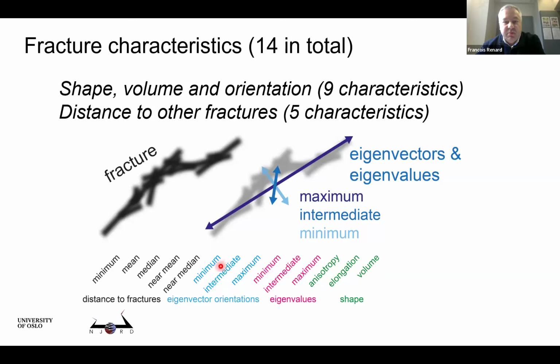There are 3 parameters that correspond to the length of the fracture. We fit each fracture with an ellipsoid, and we use the dimension in the 3 directions, what we call the eigenvalues: minimum, intermediate, and maximum. Then we also have the orientation of these 3 axes. If the long axis is vertical, the fracture is parallel to sigma 1, to the loading. We have three parameters which correspond to the shape: anisotropy, elongation, and volume. Volume is the volume of the fracture. Elongation is whether the fracture is more like a cigar or a penny shape. And anisotropy is whether it's a really circular penny or a penny elongated in one direction.